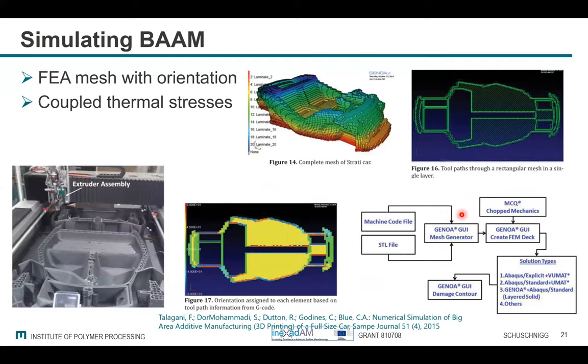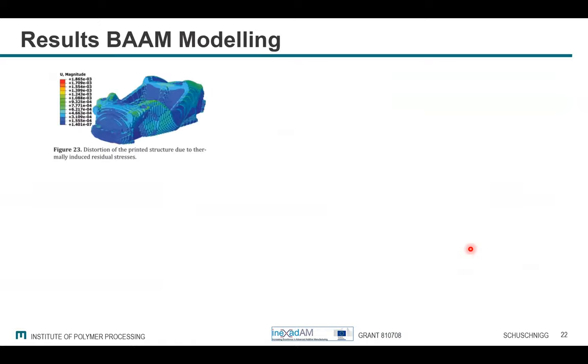This is a multi-layer, multi-scale simulation where the chopped fibers are simulated here. Then they create their FEM deck. Then they make the solution in Abaqus, and have also other simulation tools inside. And then they can calculate out of it the damage, what's happening. These, for example, are the distortion of the printed structure due to just the thermally induced residual stresses.